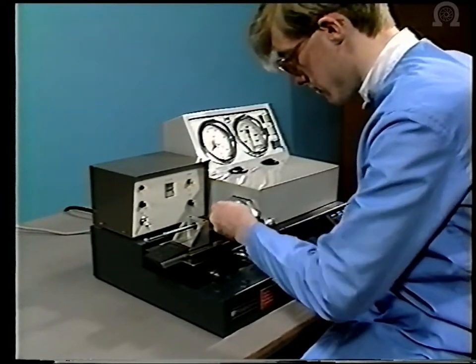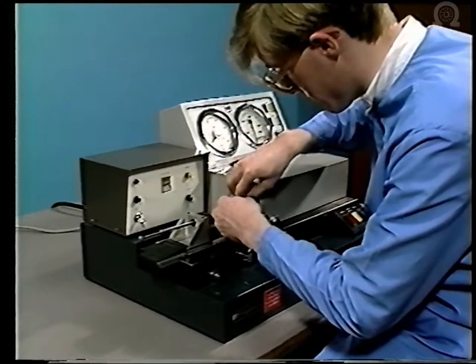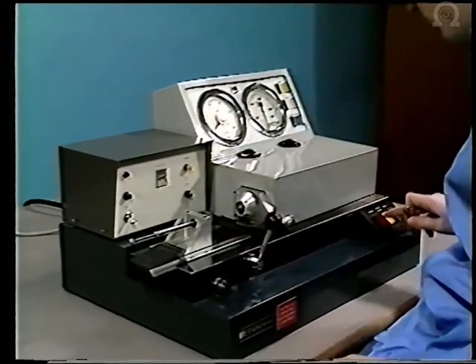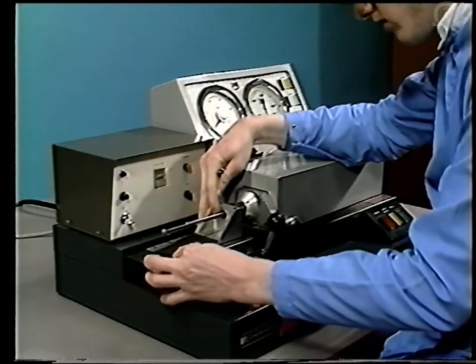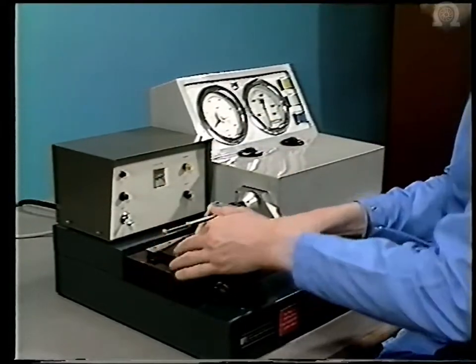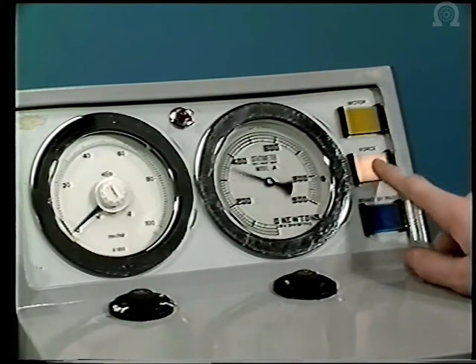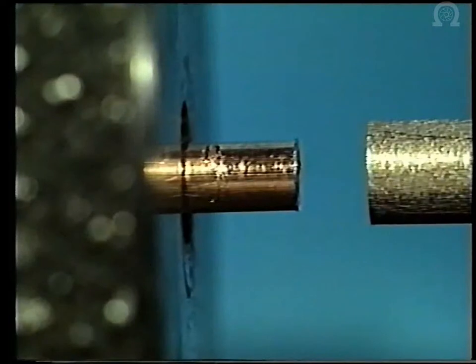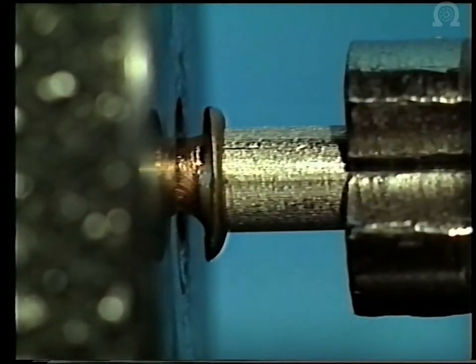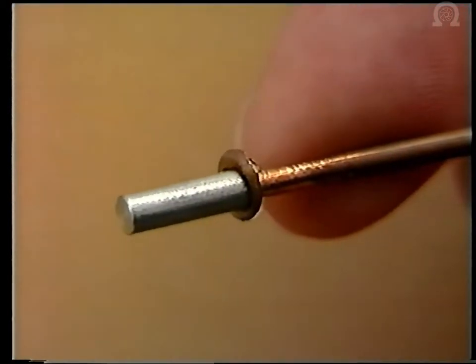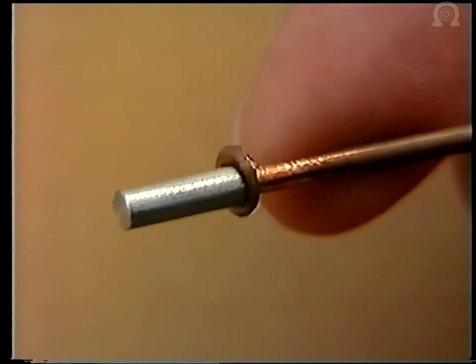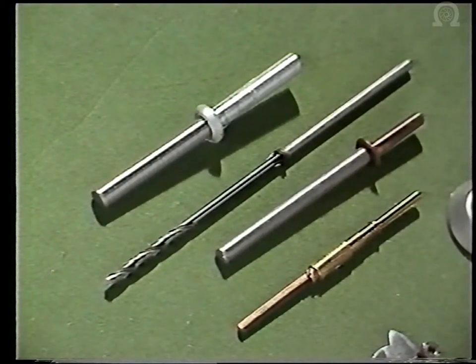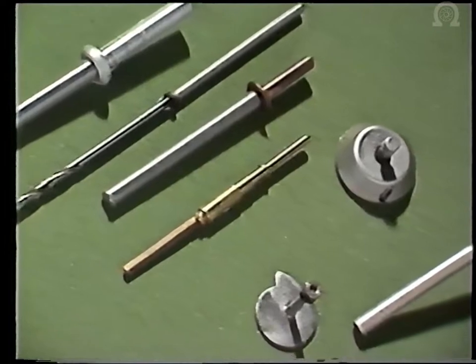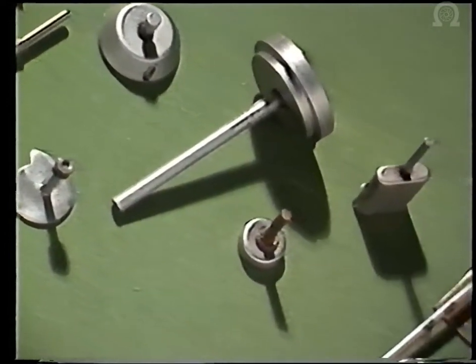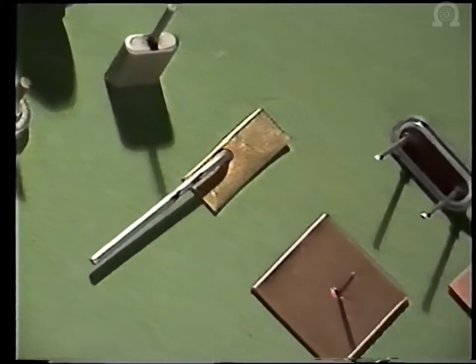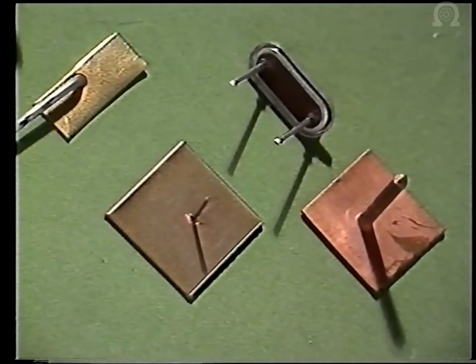Microfriction welding is particularly suited to the joining of dissimilar metals, which are difficult to weld by other techniques. This industrial prototype, developed by the Institute, can weld studs between 1 and 3 mm in diameter in approximately 1 second. Good quality welds are possible because of the restricted diffusion which occurs during friction welding. Welds between various material combinations are shown, including stainless steel to aluminium, stainless steel to carbon steel, copper to aluminium, copper to steel, steel to Kovar, and copper to copper.